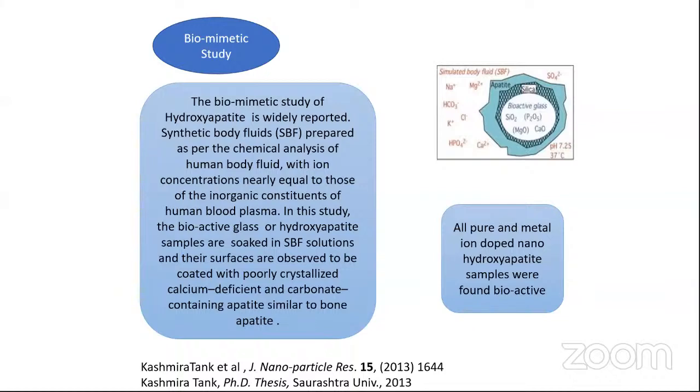So synthetic body fluid was prepared as per the chemical analysis of human body fluid, with ion concentrations nearly equal to those of inorganic constituents of human blood plasma. In this study, the bioactive glass or hydroxyapatite samples are soaked in SBF or synthetic body fluid solution, and their surfaces are observed to be coated with poorly crystallized, calcium deficient, carbonate containing apatite or hydroxyapatite. Those are similar to bone apatite.